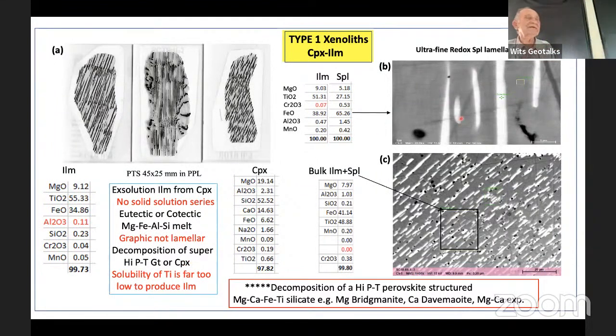Okay. So here are the new samples, and I'll show you in more detail in a moment. What I find is that in all of these, and the scale down here is about one or two microns, there are these lamellae in the ilmenite, the ilmenite component. And here it is again, these are much coarser. So what I did was to try and find out exactly what was the original composition here, where the light phase is a spinel and the darker phase is ilmenite.